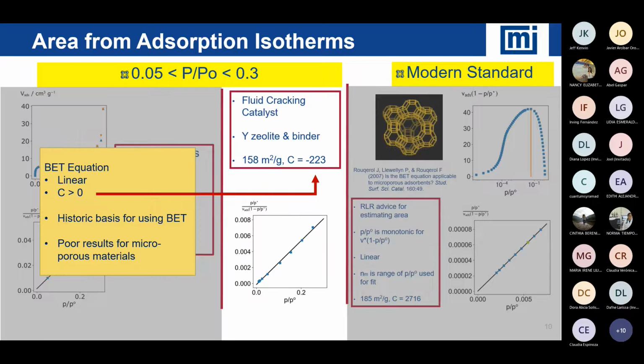We start to worry and we start to have difficulties when the material has some microporosity. So if the texture of the material has pores smaller than 2 nanometers, it becomes very challenging to properly apply BET surface area. It's a really critical application because you see from this material, it's a fluid cracking catalyst. So it's an FCC material. This is the most widely used catalyst in industry. It's used to transform heavy gas oil to gasoline and diesel. So it's a standard in the energy industry for allowing us basically every day to get in our cars and drive to work. It really helps increase the amount of gasoline and diesel available from crude oil and get the correct balance for what people need for transportation.